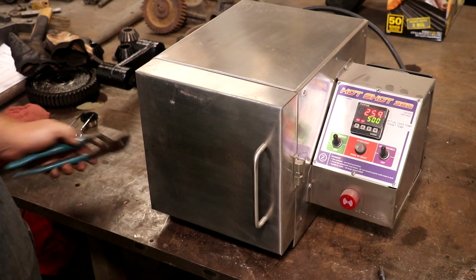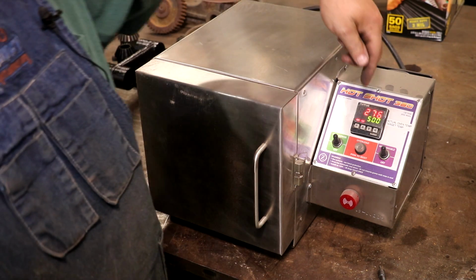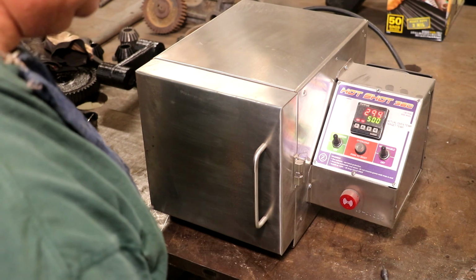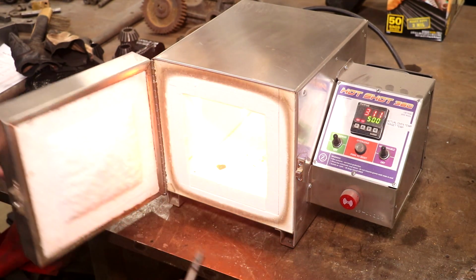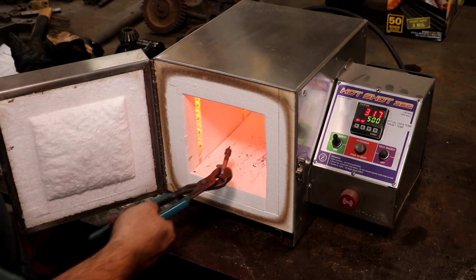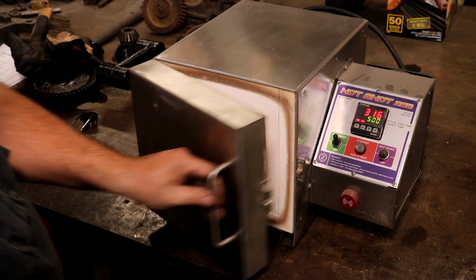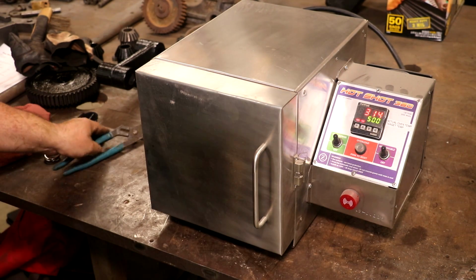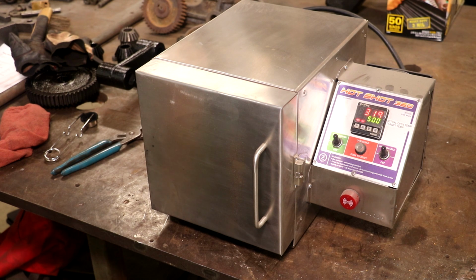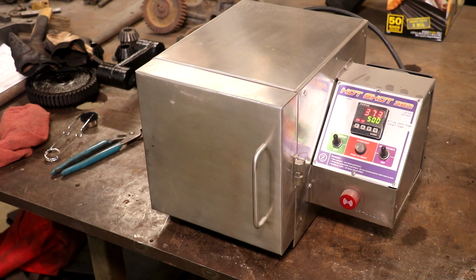Got my Hotshot 360 heat treat oven going here, and I just got it in manual mode. We're gonna go to 500 degrees. We're gonna hold it there for 2 hours. So I'm just gonna go ahead, let me turn my coils off. I'm just gonna set this in here, turn my coils back on, and we'll just let it go for about 2 hours. I'm gonna just watch the clock, and then we'll turn the heat off to it and just let it cool down nice and slow. And when we get through, according to the book again, that should get my hardness around Rockwell, what was it, 47 to 50, somewhere in that ballpark.